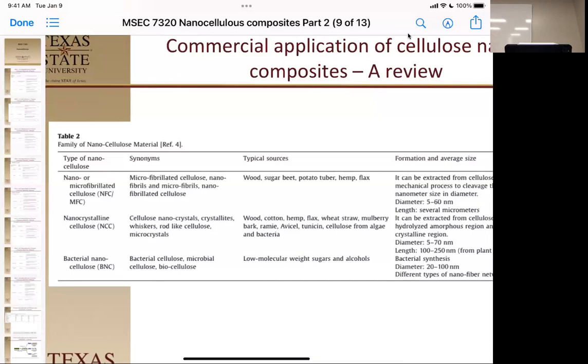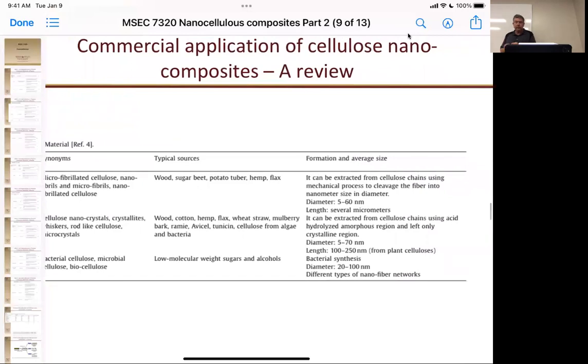Okay, so in this case, the nanofibrillated cellulose can be made from nanofibers or microcellulose fibers. It can come from a lot of different sources, and can be extracted mechanically with decent lengths and diameters between 5 and 60 nanometers. But look at it, several micrometers long. That's a big aspect ratio. You can modify that by the type of mechanical processing you do. If you're doing physical ball milling, you actually get longer fibers than with high shear homogenization, because in high shear homogenization you have them whipping around and they start breaking apart. So your process also controls the final product, not only your starting material.